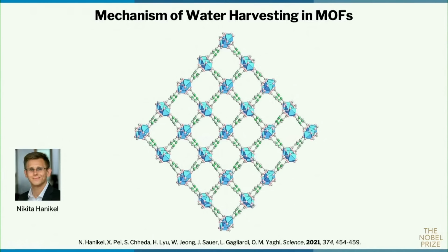We've characterized this with single crystal X-ray diffraction, so this is not just an artist's rendering of the structure, but rather it comes from real data on the positions of the atoms. I'm going to slice out one of the pores to show you where each water molecule sits, again characterized by single crystal X-ray, and study the binding sites of water.